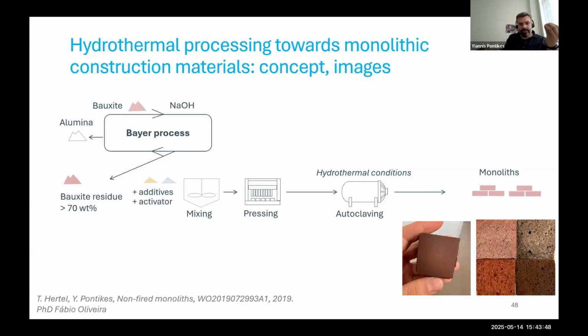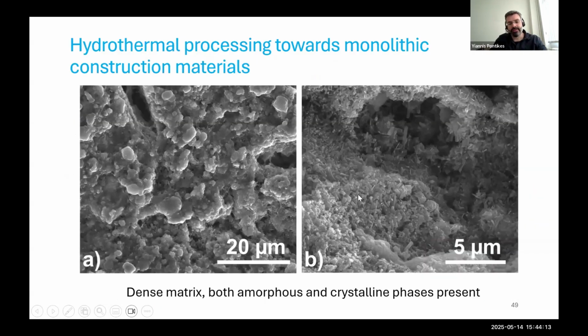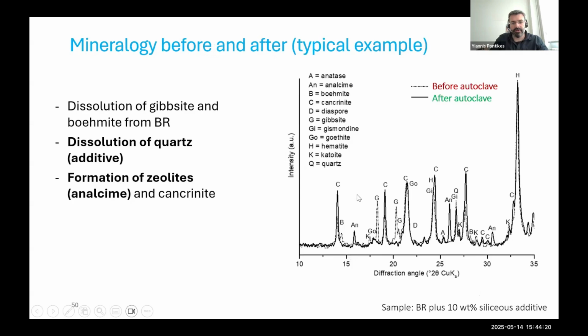That's how you do the Bayer process. It means that you need high temperature and pressure, and then things start to dissolve. And that's how you do also many building materials. You use autoclaves. And we thought this is a low capex process. And in fact, it does create interesting products that, of course, are water insoluble. And that's all it takes. So you make bricks through this autoclaving process, and you make your monoliths. Here you see microstructure. It's quite dense matrix. And I will show you now another slide, what is forming, different things.